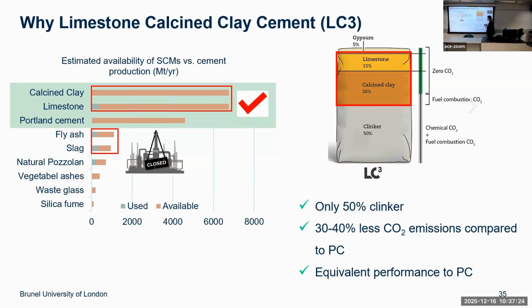Okay, limestone. The reason is that calcined clay, you can find everywhere across the globe, and the same goes for limestone. While other SCMs, supplementary cementitious materials, are getting less and less, especially in Europe, such as fly ash. In the UK we have closed down all these coal-burning power stations, so we wouldn't have fly ash anymore. And steel slag: manufacturing of steel is winding down significantly in the UK. We only have two plants now making steel, and one of these plants still requires government subsidy, otherwise it could close down. If they close down, we wouldn't have steel, and slag, GGBS, is now a similar price to Portland cement. So that's why many research efforts now move to LC3.